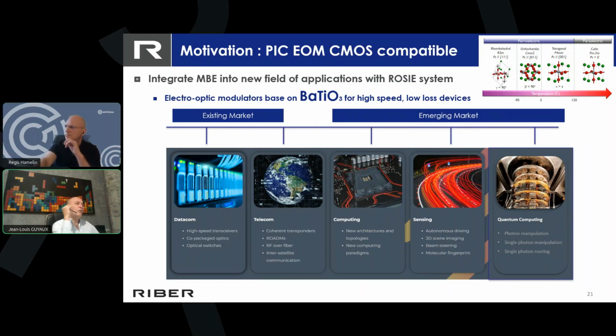Exactly. When you start growing, you need to bring energy to the atoms to arrange, to build the crystal and so on. So you are at high temperature. Thus, you will grow the material at a temperature between 300 degrees and 650 degrees. At that time, you have the material in cubic phase. This is paraelectric because you are above the Curie temperature. However, when you cool down the material to extract it from the growth chamber, you will have a phase change, which usually occurs at a higher temperature because we are building thin films of BTO, and it becomes tetragonal.